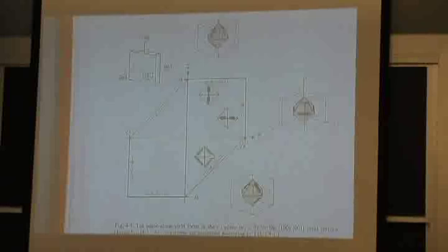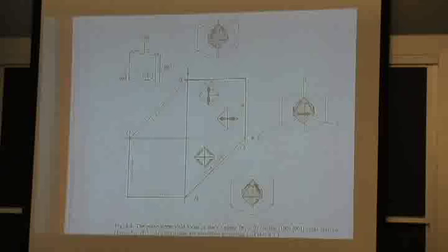And without 5, I cannot get an arbitrary shape change. And so if I have real FCC material or BCC material, and the grains are large enough, when I pull on it, I'm going to get an orange peel surface, just like that piece I passed around, right? It's inherent in the crystalline behavior of the material.